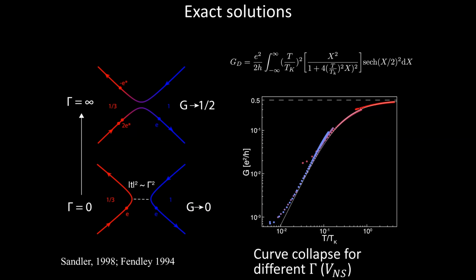The dominant process, when you try to inject, is that basically at this fixed point, 2 electrons come in, or 2 quasi-particles come in that have e/3 charge each. 1 electron goes across, sorry for the bad resolution here, and a negatively charged hole is retroreflected into the upstream mode. This is basically analogous to Andreev reflection at a superconductor-metal interface, where an electron comes in, a Cooper pair goes out, and a hole is retroreflected. It comes from the fact that you have a boundary between a state where the low energy excitations have one type of charge and the other where they have a different multiple of that charge.